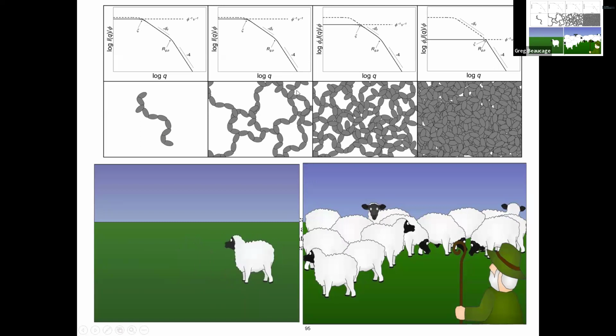Because they're overlapped. You can still see the same thing at a small scale. So the intensity divided by concentration is the same at the high end, but this low end starts to get swamped out because you can't see the fibers anymore. What you see is actually a real correlation length, the size of the hole in the system. What's the spacing of the things? So you can see up to that point. Beyond that, at lower magnifications, it starts to just look like a sheet, like you just see uniform.